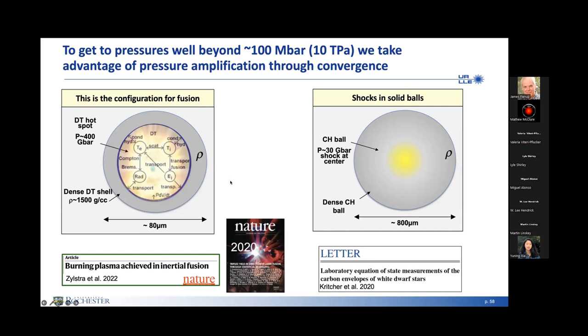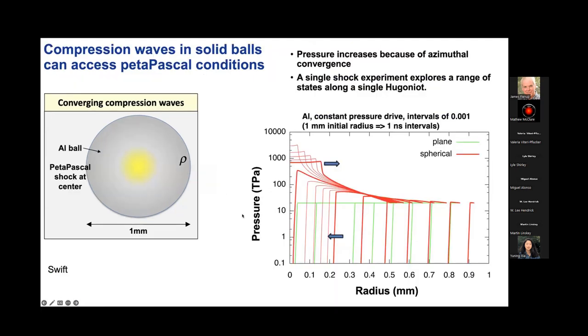So what we do is we use the laser energy, the laser intensity that we can, and we shine it on spherical systems. And then we launch compression waves that move in spherical geometry. Then when they get to the very center, it gets to very, very high pressure. And so we can do that in balls, or we can do that in shells. And so this is an example of a ball, where we just take a plastic ball and we just shine lasers on the outside. That launches a compression wave.